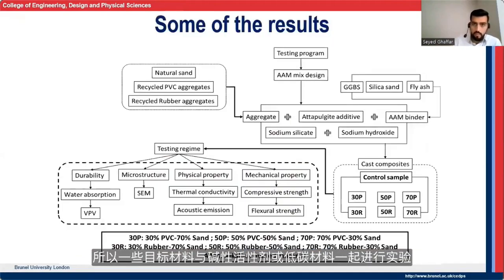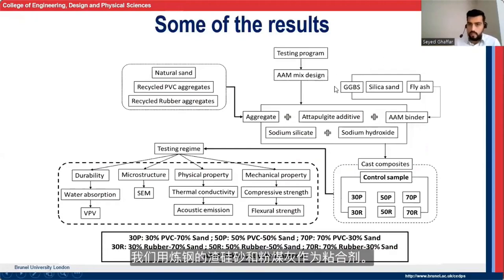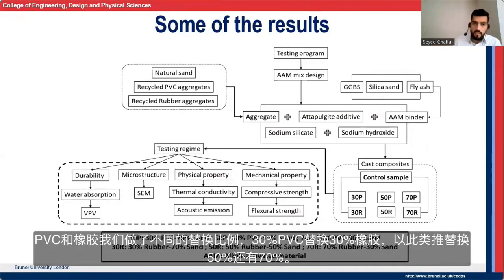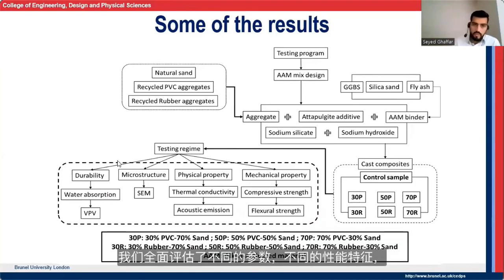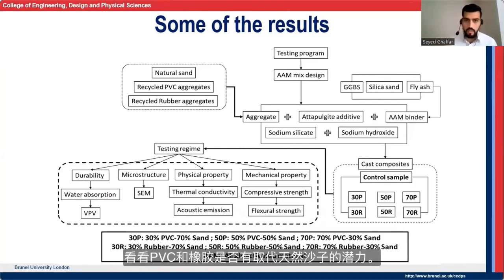So some of the results, we worked with alkali activated materials or low carbon materials. Some people call it geopolymer. We had slag from the steel manufacturing, silica sand and fly ash as our binders. And the aggregates that we used were obviously natural sand for benchmarking purposes, PVC and rubber. We made different replacement ratios, 30% PVC replacement, 30% rubber, 50 and also 70%. And we assessed quite comprehensively different parameters, different performance criteria in order to see if the PVC and rubber have the potential to be replacing natural sand.